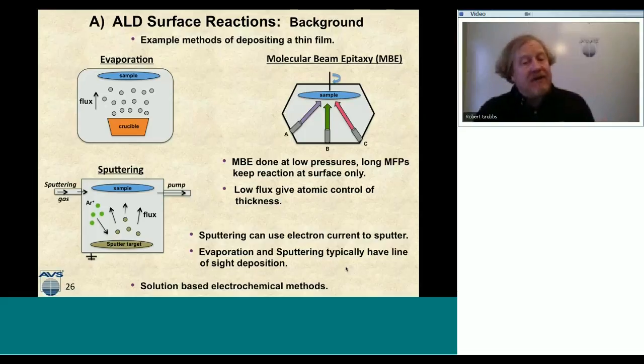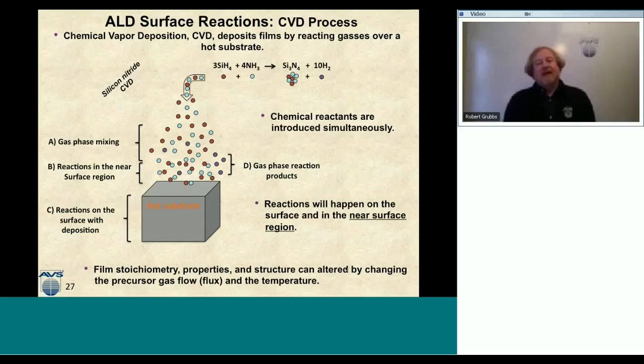Now there's one more method that's actually very close to ALD, and that is chemical vapor deposition, or CVD. On the surface, chemical vapor deposition just deposits film by reacting a mixture of gases over a hot substrate. But there's a little bit more detail in that. In chemical vapor deposition, we bring in the reactants simultaneously. They go through the same shower head, the same piping. We mix them up, and they mix before they get to the hot substrate.